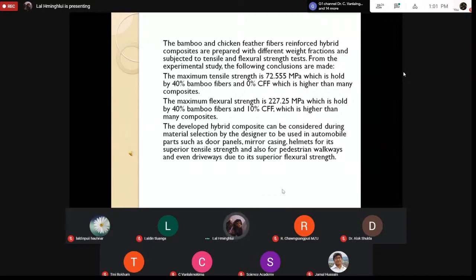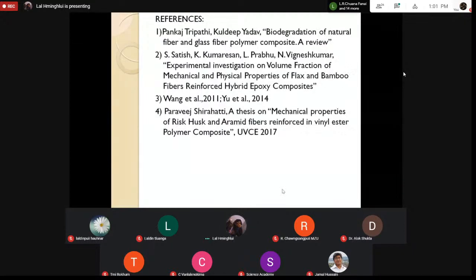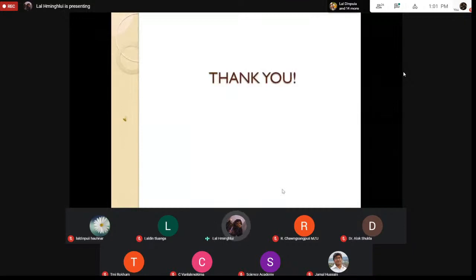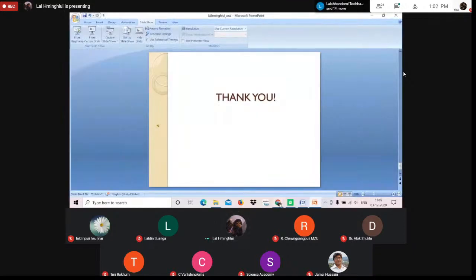The maximum flexural strength is 227.25 megapascals, which is held by 40% bamboo fibers and 10% chicken feather fibers, which is higher than many composites. The composite can be considered during material selection by designers to be used in automobile parts such as door panels, mirror casing, and helmets for its superior tensile strength, and also for pedestrian walkways and even driveways due to its superior flexural strength. So here are the references that I have used for this paper, and thank you for your time and your patience.